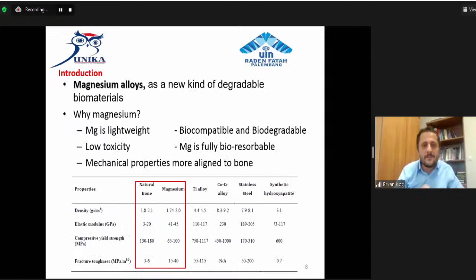Magnesium alloys are a new kind of degradable biomaterials. Magnesium is a lightweight metal with a density of 1.74 grams per cubic centimeter, which is 1.6 and 4.5 times less than aluminum and steel, respectively. And it has an elastic modulus of about 44 gigapascal. This is low compared to other metals used as implant materials.